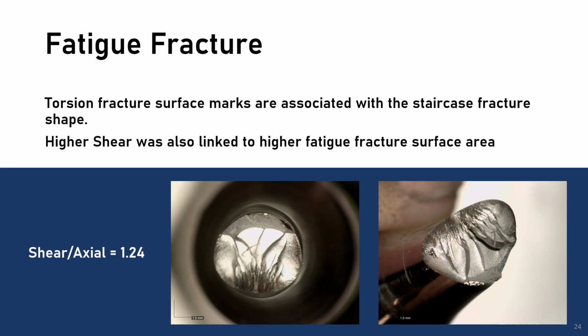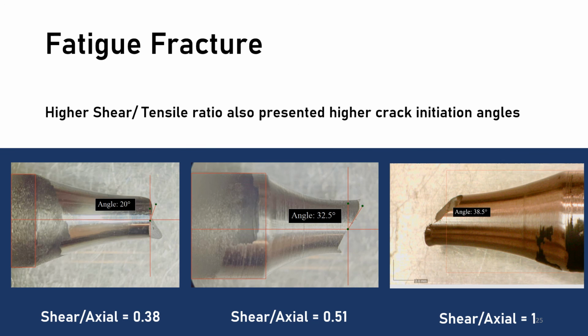Looking at the same specimen with higher shear to axial stress amplitude ratio, we can observe the staircase fracture shape associated with the torsion damage applied to the specimen. Another parameter differentiating different ratio specimens is the crack initiation angle, where we can observe a direct increase in the angle as we increase the shear and axial ratio.